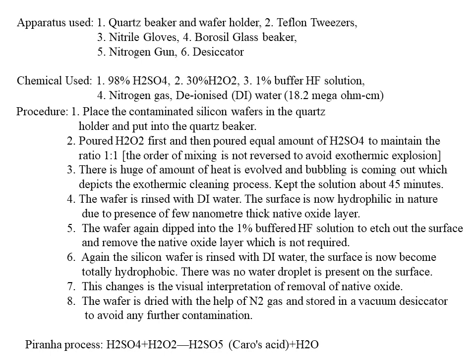But we plan to grow our silicon oxide in a very defect-free and uniform nature, so we have to remove or etch out this native oxide. So in the next step, this wafer is poured again into the 1% buffered HF solution to etch the surface for removal of native oxides.